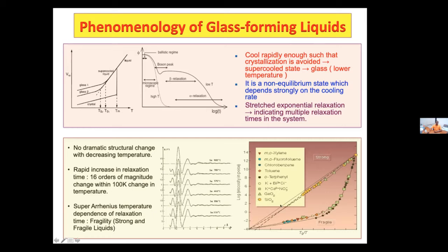For a strong liquid, if you plot the logarithm of viscosity as a function of inverse temperature, viscosity grows linearly, following Arrhenius type behavior, telling you that the typical energy barriers that the system has to overcome are probably not changing significantly with changing temperature. And there is another class of glass forming liquids where viscosity changes very rapidly, for example OTP, orthoterphenyl, which belongs to this lower end. There, in the low temperature part, the viscosity grows very rapidly, and sometimes this growth can be extremely large. For example, over a change of temperature of roughly 50 degrees, viscosity can change by 10 to the 10, 12.